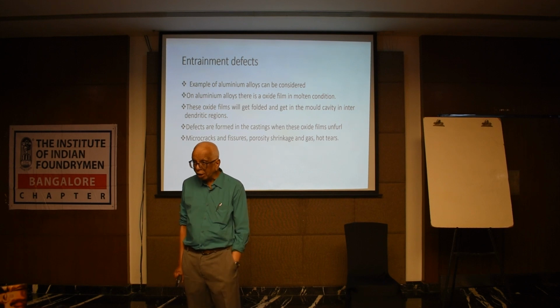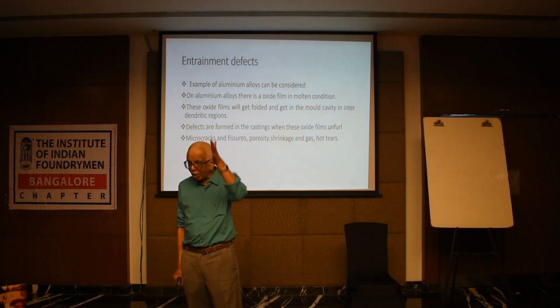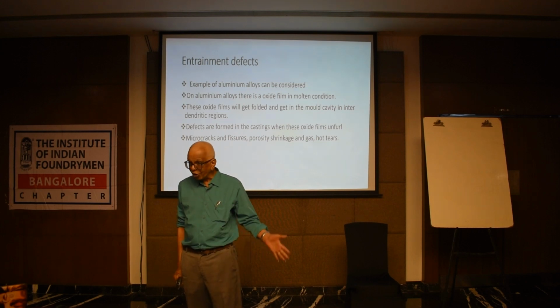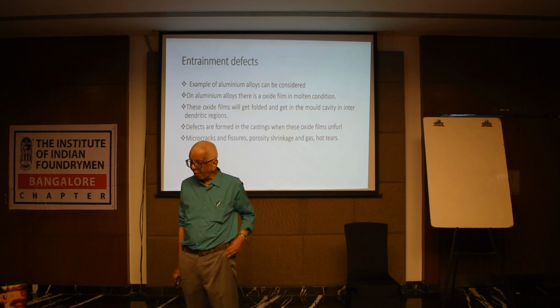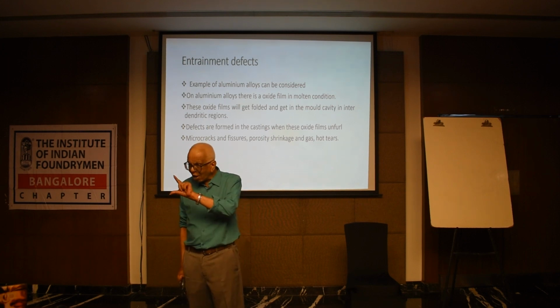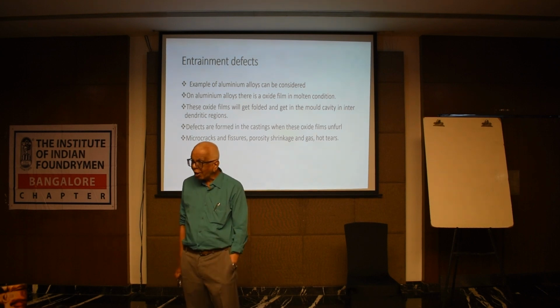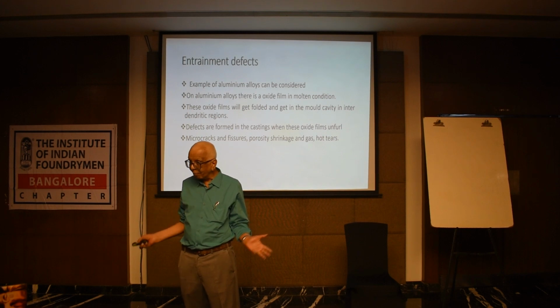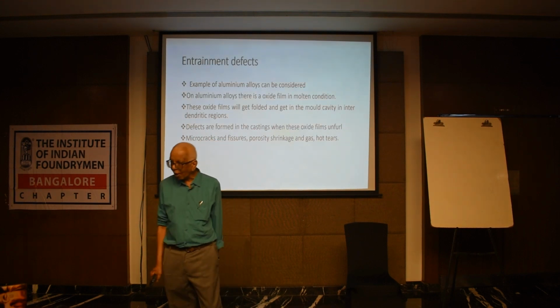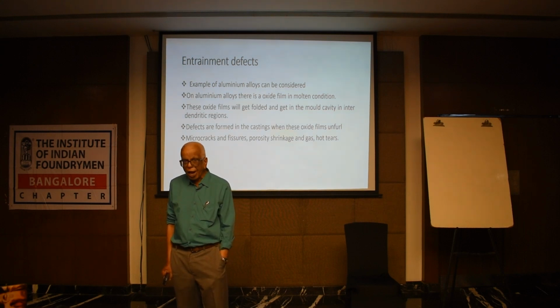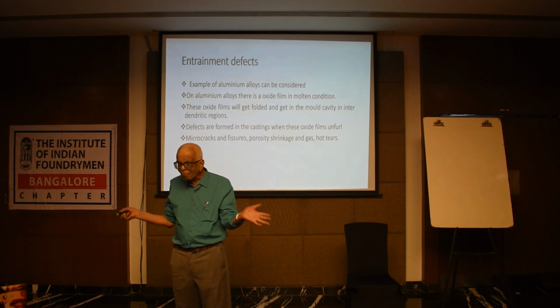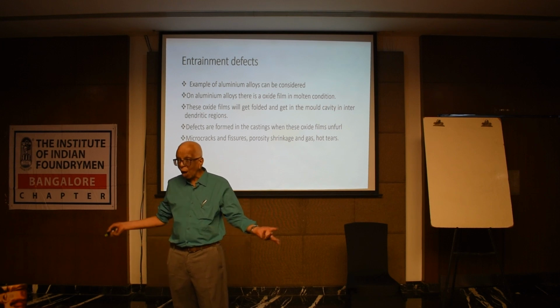Everything is dendrites in solidification. The flat liquid interface breaks down into a cellular interface or a dendritic interface. So the bifilms get furled and entrapped in the interdendritic areas. Those are called entrainment defects when bifilms get into the mold cavity in the casting. Now, the problem begins during unfurling. It leads to porosity like gas porosity, shrinkage, hot tears, all the defects in castings from unfurling of the bifilm. And that's how I understand it.